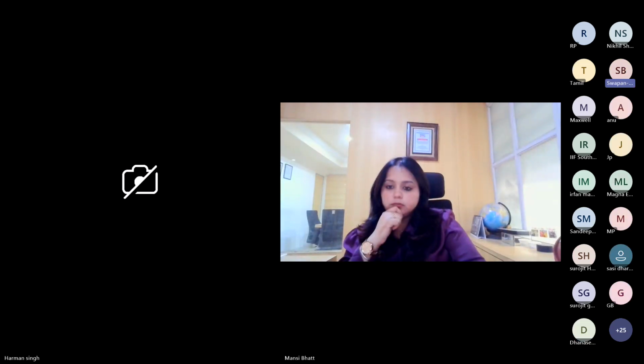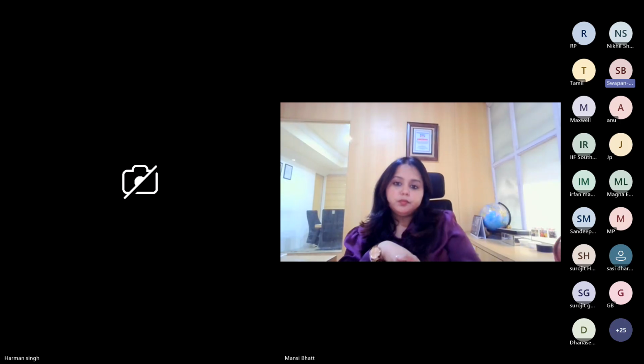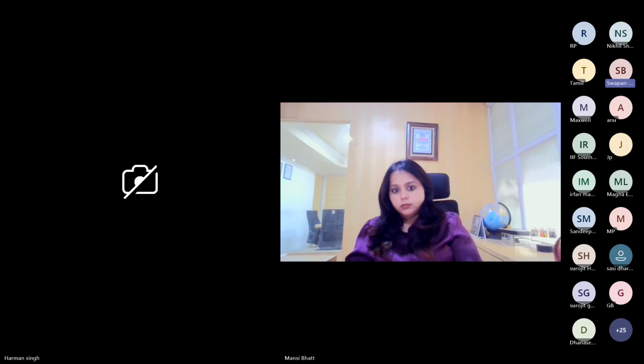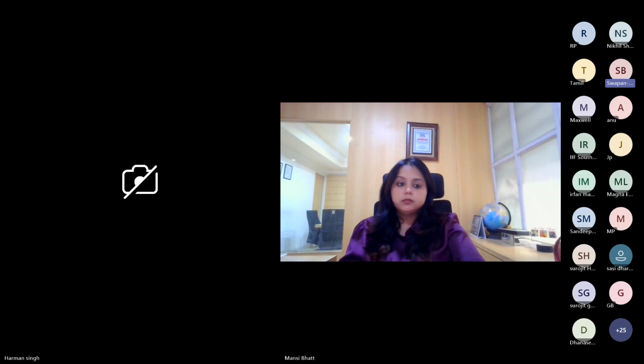But along with that, you also have to think about your base metal condition. If nucleation sites are on the lower side, then you need to correct the metal nucleation sites, maybe by adding silicon carbide or a strong preconditioner. I already explained this, zircon aluminum content. It will help to increase the nucleation sites in the furnace. After that, if you go with this cerium containing inoculant, it will help further to increase the nodule count.